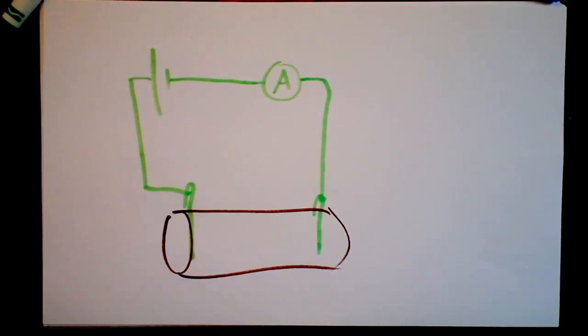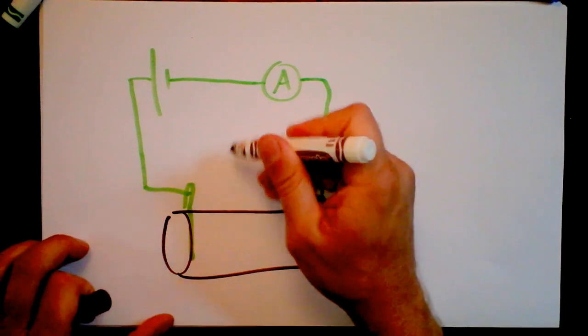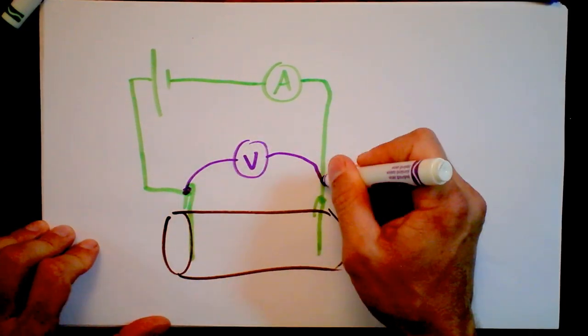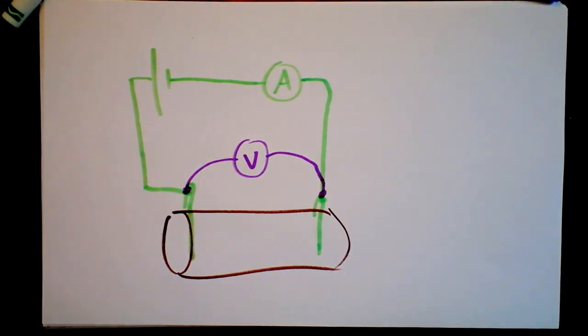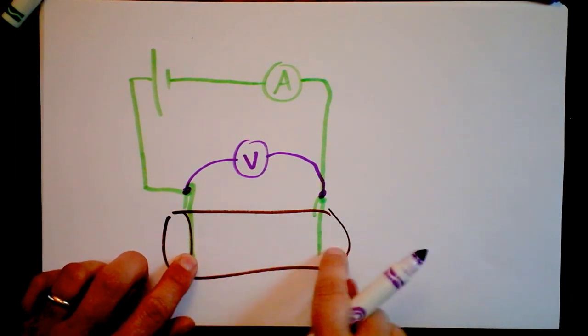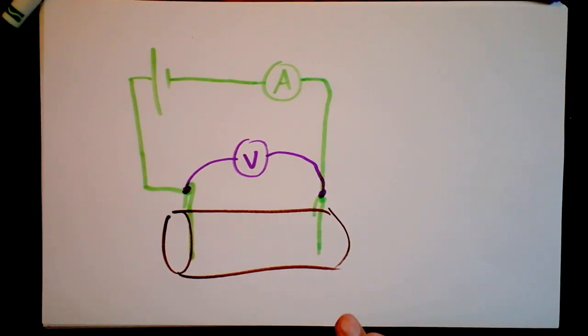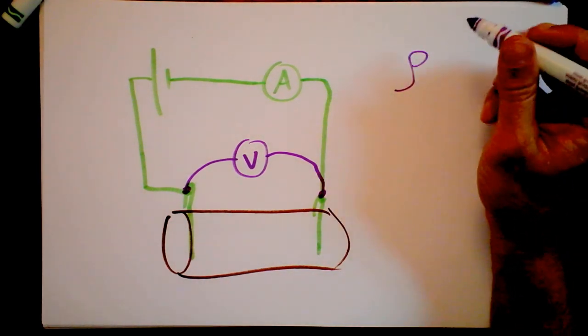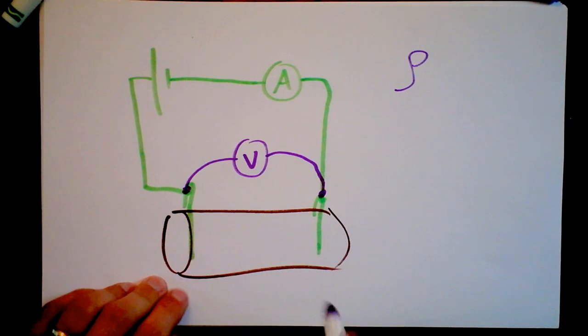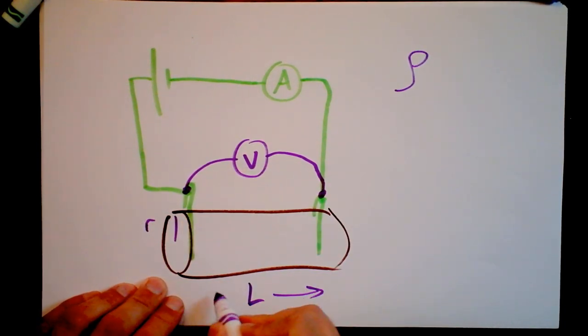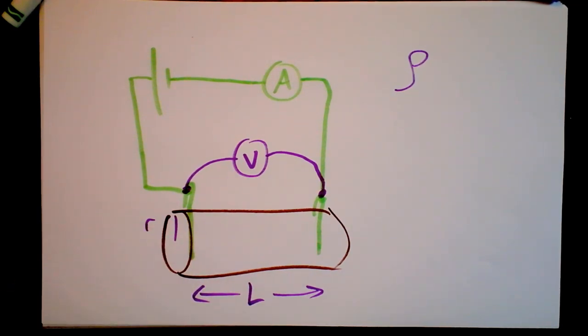Now, if you come over to this sucker with your voltmeter and you attach, you take your voltmeter and you clip it on to here and to here, then you're going to be measuring not only the resistance of the dough, which we're trying to get to the resistivity usually. And probably that has something to do with the amount of the material. So as you change this radius right here, and as you change the length between those two, then that allows you to get at like the essential, like what is the resistivity of some bulk of this material. That's neat, right?